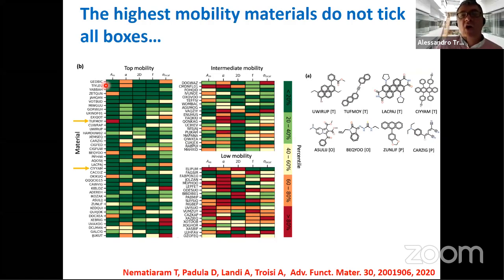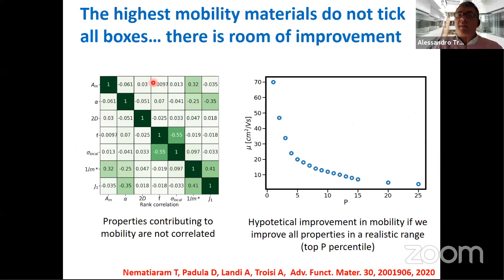First, you need to check that all the components that contribute to mobility are uncorrelated, otherwise you cannot improve one independently from the other. And then you can perform a hypothetical experiment where you improve all components, all contributors to the mobility, in such a way that you simulate the generation of an ideal material within the realistically available range. This is, I think, my last slide. So we show, with no time to look into the numbers, that there is no correlation between parameters that affect the mobility.